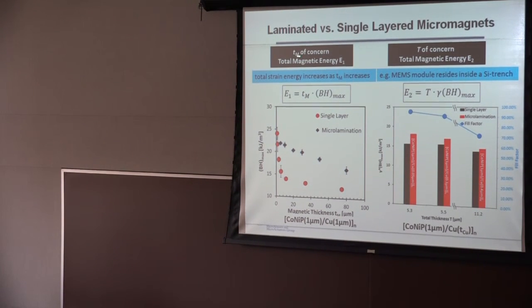The first is when the magnetic thickness is of concern, and the second is when the total thickness is of concern. Let's talk about the first case. As we know, there exists very high residual stress in the magnetic layer, and when you increase the magnetic thickness, the total strain energy also increases. In this sense, delamination is the factor that prevents you from getting an even thicker film. So in this case, the total energy is related to the magnetic thickness rather than the total thickness.